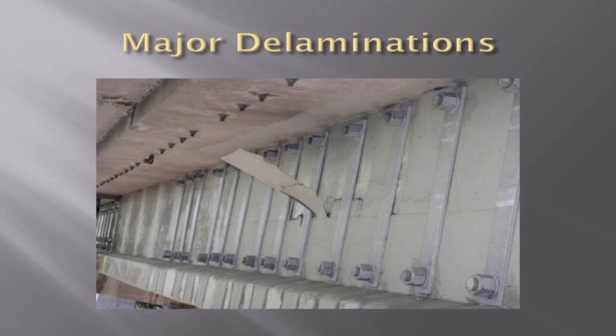Major delaminations. Here's an example of major delamination. This is actually on the Winchester Bridge, which they flew the drones on. As you can see from this picture, this structure has had lots of retrofit. We've got shear banding, and we have FRP strips. There's an interesting crack going down that you can see. I'm not sure what's going on there, but we do have an obvious major delamination. That's not very common. That's only one bridge out of everything on our inventory, and that's only one strip out of many strips on that structure.